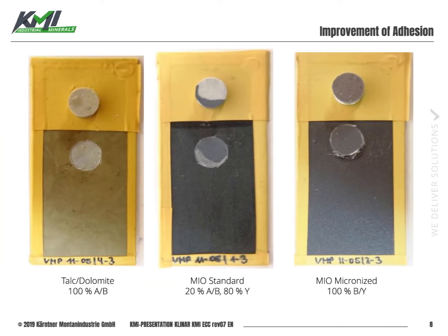The third effect of MIOX is the improvement of adhesion. That means the improvement of adhesion on substrates, but also the intercoat adhesion. What you can see here are three test panels. The substrate is galvanized steel, so hard to coat. On the left hand side you can see a 2K epoxy filled with a mixture of talc and dolomite, which is a typical filler material. In the center you can see again a 2K epoxy with MIOX standard grade, and on the right hand side you can see again 2K epoxy filled with a MIOX micronized grade, again at the same